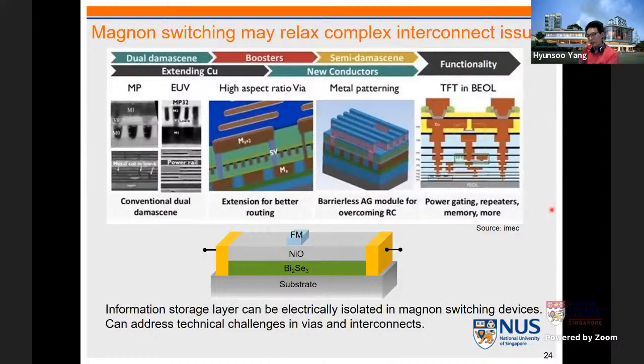And if we can realize this, I think this can also be useful to mitigate the loss from the complex interconnect issue in modern CMOS and any semiconductor chips. If you look at the cross section of this chip, we have a functional layer in the first layer, and then we have an additional 20 to 30 layers for interconnects. The role of this interconnect is connecting from one device to the other device. So we have local contacts, and then we even have global contacts and so on. We need to make holes and then fill them with copper. These holes are called vias, and this is a very, very complex and difficult issue in modern semiconductor and memory chips.